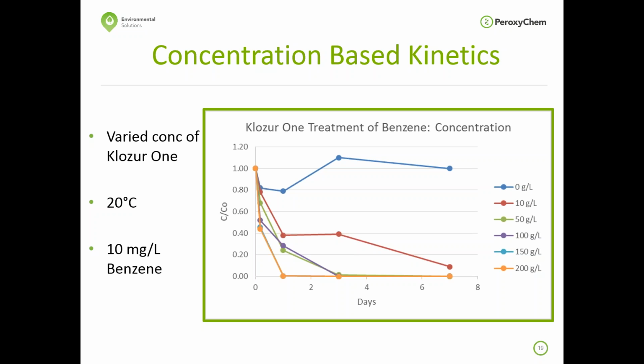It was well into the high 90% reduction range. And then by 7 days, even the 50 gram per liter system, all systems at or above 50 grams per liter Klozur One were non-detect. And the 10 gram per liter system, you can see, was in the mid-90s, or right around 90 to 95% mass or concentration reduction within the 7 days. So with increasing concentration, you saw increasing rates of reaction with the contaminant of concern.